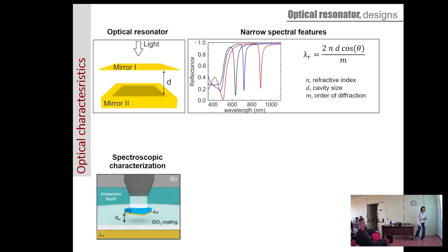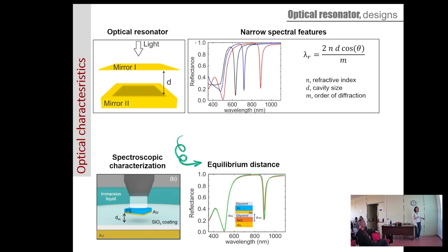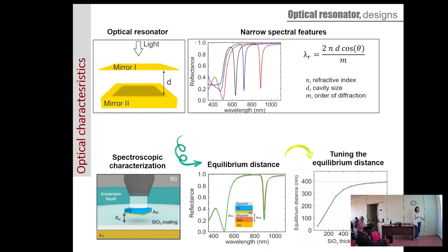So, the idea is the following. We are going to build an optical resonator where one of the films is levitating over the other. We are going to characterize it spectroscopically. We are going to have something like that, and from this kind of measurements and from some fittings, we can extract the equilibrium distance of our system, and then by changing the refractive index, like layering differently in between the two mirrors, we can tune this equilibrium distance and build different optical resonators.